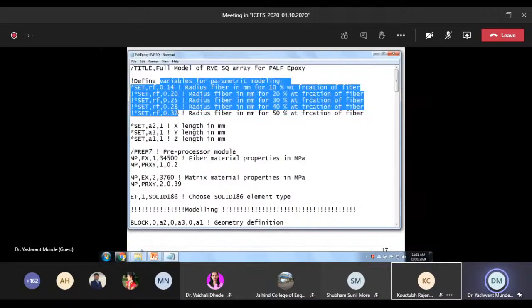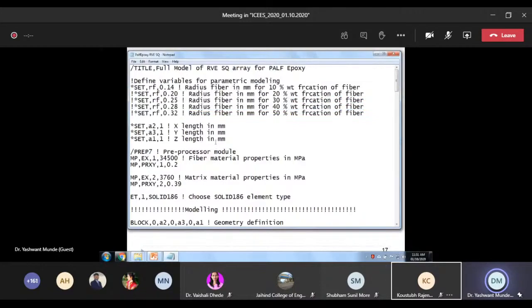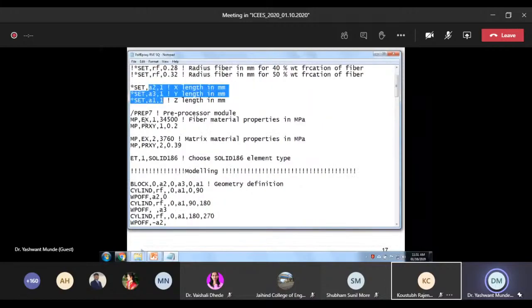I have taken the RVE size to be 1 mm by 1 mm by 1 mm. So these are my A1, A2, A3 values. Then I give the input properties of the material. The elastic modulus of the fiber material is 34,500 megapascal, and the Poisson's ratio of the fiber is 0.2. Whereas the property of the matrix is 3760 MPa, which is the Young's modulus of my matrix material, that is epoxy, and the Poisson's ratio of the matrix material is 0.39.